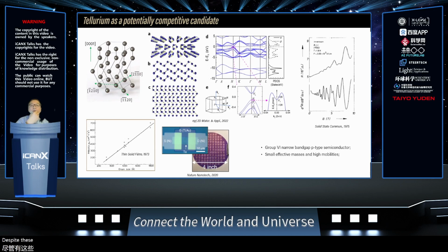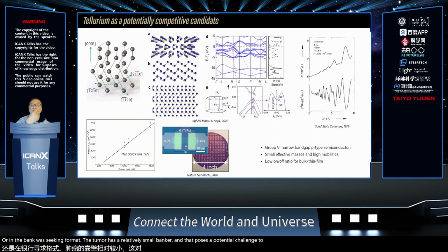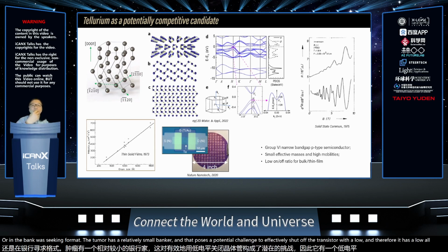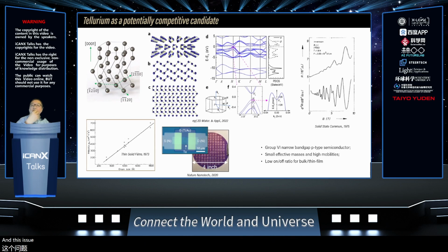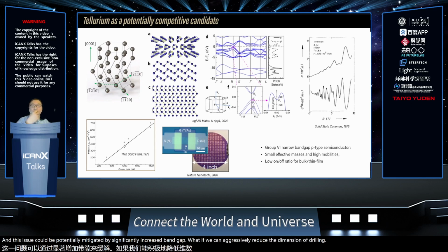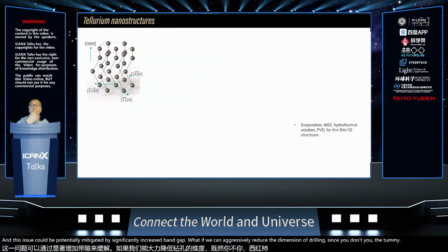Despite these superior electrical properties of tellurium for advanced technologies, in the bulk or thin film format, tellurium has a relatively small band gap, and that poses a potential challenge to effectively shut off the transistor, and therefore it has a low on-off ratio compared to other semiconductors or silicon transistors. And this issue could potentially be mitigated by a significantly increased band gap if we can aggressively reduce the dimension of the tellurium thin film down to the atomic two-dimensional limit.